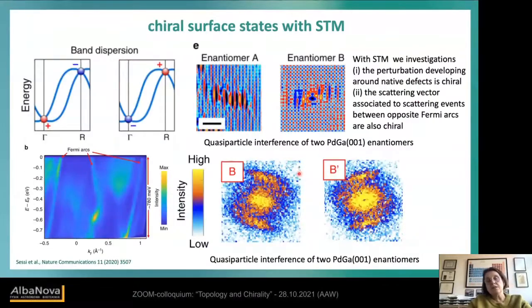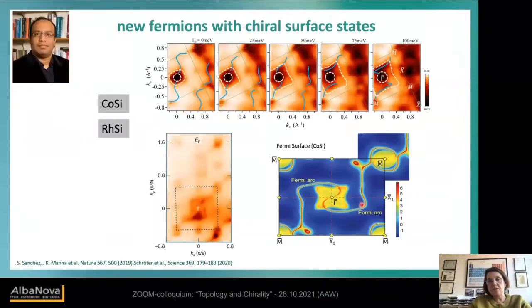Okay, so we also did STM investigation, and it's a little bit surprising since there is only a difference in the phase, but even in the quantum interference, you see nicely that the enantiomorphs have different chirality in the pattern of the STM, because there is an interaction between the surface state and the bulk, which is strong enough to see that we have chirality here.